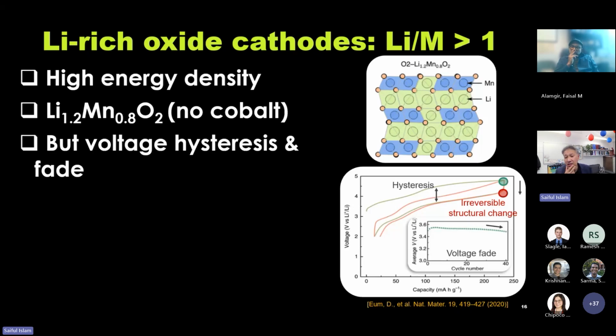On the bottom right is some experimental data, some voltage capacity data, showing that there is a problem. There is some first cycle hysteresis, and there is some irreversible structural change. But also over many cycles, there is some voltage and capacity fade.